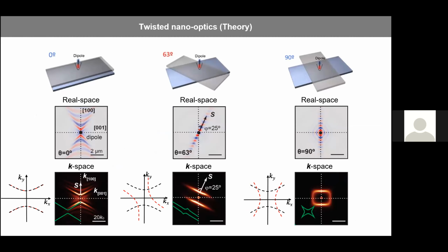Yeah, this is actually a very good question. I need to explain a bit here, because the physics behind this work is a bit different from the physics of the magic angle in graphene. Here the physics behind it is just interlayer electromagnetic coupling, and the magic angle is not so sensitive to 0.1 degrees. It's more like 1 or 2 degrees, and then you will remain in the magic angle. Thank you for the question.